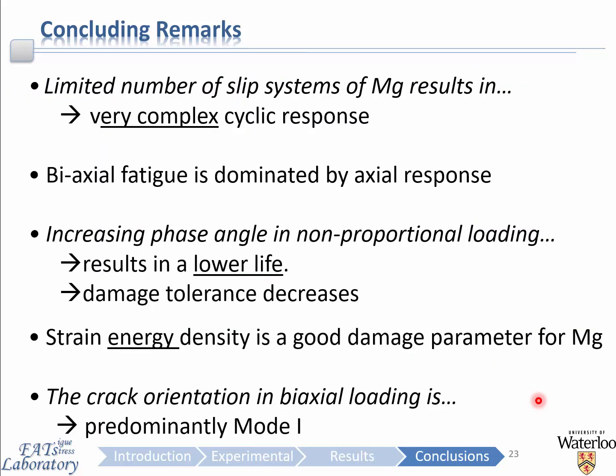In conclusion, near net shape closed eye warm forging of extruded AZ80 magnesium results in a structure that yields both good strength and ductility for automotive suspension applications. Some concluding remarks are, due to the limited number of slip systems available at room temperature, the cyclic response of magnesium is quite complex, as illustrated in the presentation. The rotation of the principal axis in non-proportional loading causes damage to accumulate along different planes and a lower life, which is typical of a ductile material.